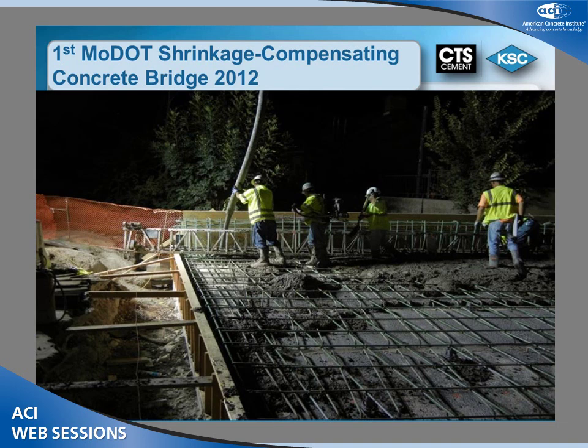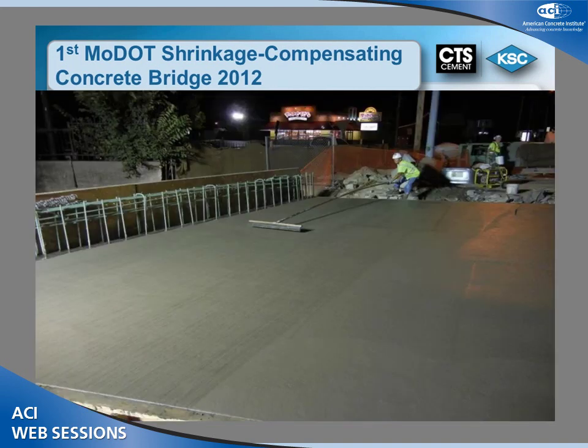We actually increased the cement content because we were looking for a 3-day turnaround. We needed 4,000 PSI in 3 days. Now, this was not rapid set, as was asked earlier. This was actually the shrinkage compensating cement component, as well as Portland cement, and we just increased the amounts. We did a 3-day wet cure, and they basically put a curing compound on it after that 3 days and opened it to traffic. We had our 4,000 PSI.